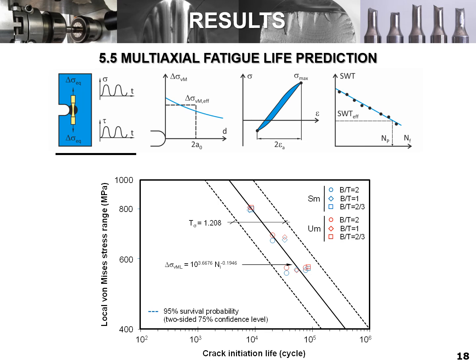The first step, as represented, is the reduction of the multiaxial stress state to an equivalent uniaxial state. This step was done via the equivalent von Mises stress range. As can be seen, there is a very good correlation between the von Mises stress range evaluated at the initiation site, either for the structured or the unstructured meshes. In addition, the values determined in both cases are rather similar.